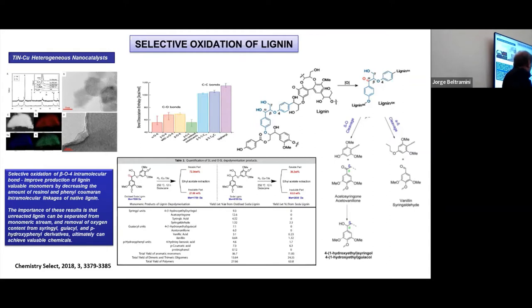And at the end of the day, working with individual compounds here, we see that we can produce very selective esters like the vanillin and also the hydroxyethyl guaiacol. When we compare the oxidized lignin with the non-oxidized lignin, you can see in this particular table that the total amount of aromatic monomer that we produce is nearly 60%, compared to only 12% when the lignin is not oxidized at that particular function. Why? Because without that function, the total amount of polymer and dimeric and trimeric oligomer is very high, because they break in any way. And that will be very difficult to do.